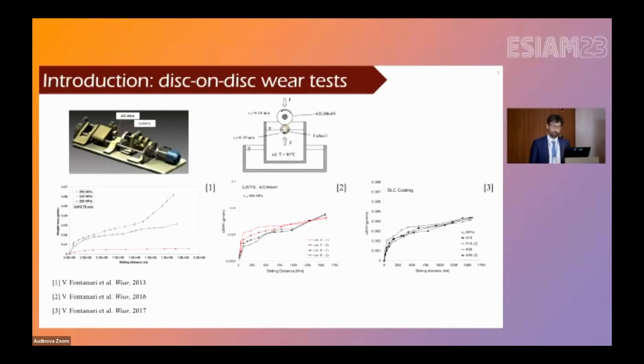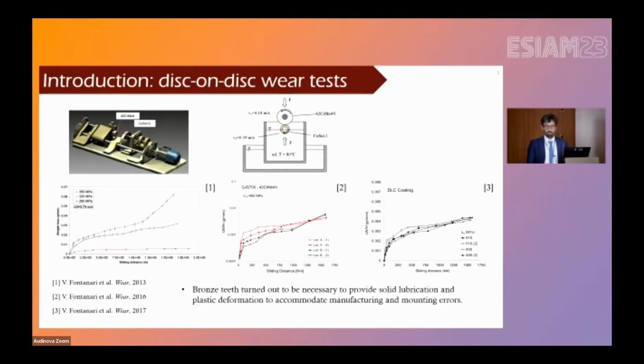At the beginning, the results were very promising. We were able to reduce the wear rate of the tribological pair a lot. So we tried to fabricate a prototype of a gear set in which the worm wheel was made of cast iron, but the results were catastrophic, in the sense that the wear rate was not the problem here. The problem was the unacceptable level of vibration and noisiness. And so we came to the conclusion that in some way, bronze is necessary at the contact between the teeth, because bronze has the peculiar characteristic of being a solid lubricant and has the necessary ductility to adapt itself to accommodate inevitable manufacturing and mounting errors.